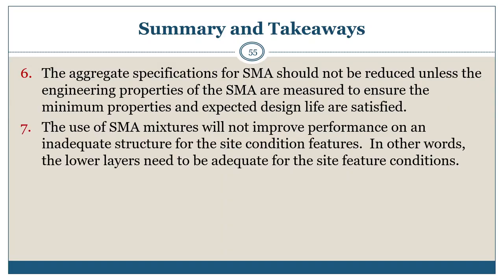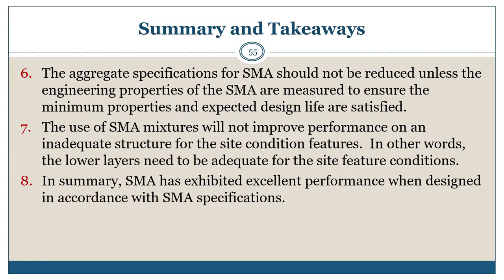The use of SMA mixtures will not improve performance on an inadequate structure for different site condition features. In other words, the lower layers need to be adequate in terms of design and construction for the site feature conditions. In summary, SMA has exhibited excellent performance when designed in accordance with SMA specifications. The most important takeaway on this slide is that if you decide to reduce the aggregate requirement so that local aggregates can be used, make sure the performance tests are run to confirm the mixture is still resistant to deformation and fracture.